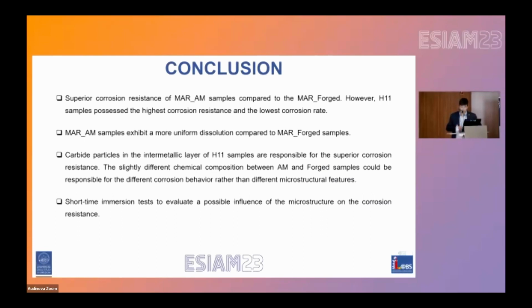In conclusion, it's possible to say that immersion tests highlight the superior corrosion resistance of the additive manufacturing samples compared to the forged one. The H11 sample possesses the highest corrosion resistance and the lowest corrosion rate due to the presence of chromium carbide particles in the intermetallic layer. The maraging additive manufacturing sample exhibits a more uniform dissolution compared to the forged one, which can be related to the different speed of dissolution, but also probably to some effect related to the more uniform microstructure of AM samples.